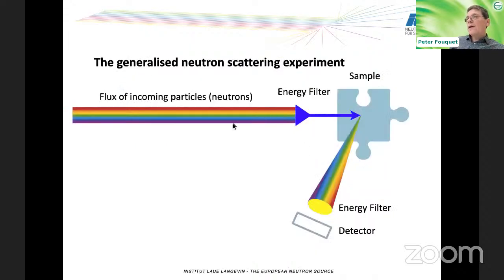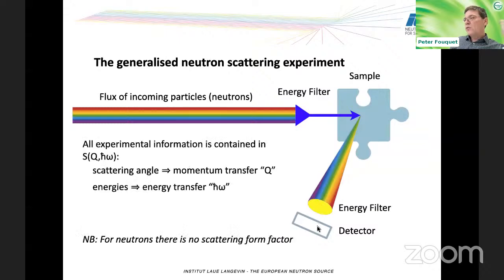Now, in a generalized way, what you do in a neutron scattering experiment or any spectroscopy experiment, you come in with a pretty white beam. You apply an energy filter, do scattering from the sample. Then you apply a further energy filter and you measure the signal in the detector. And the information that you extract, you normally categorize by splitting it up into what's happening at different momentum transfers and different energy transfers. And you do that because splitting it up in this way gives you a lot of information that lets you compare the data to, for example, molecular dynamics simulations.